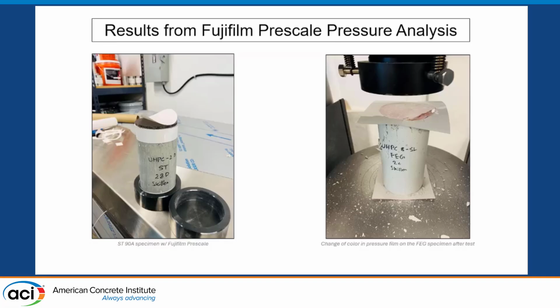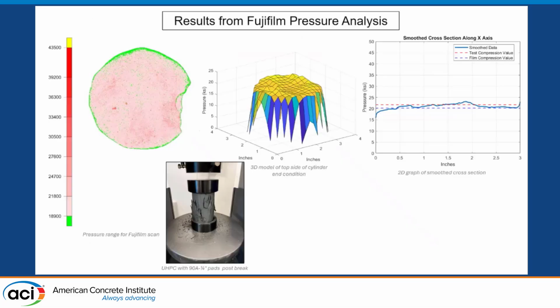Likewise on the top. For the fixed and grinded condition, you can see on the right, there's no pads needed, so we just put the films right on top. And the results from this were really interesting. These pressure films had an associated scale range, as you can see on the left-hand side. So it was between 18.9 KSI and 43.5 KSI.